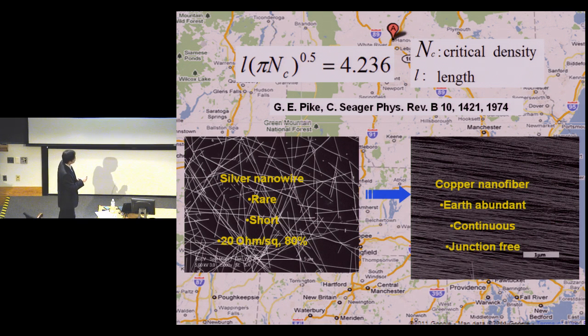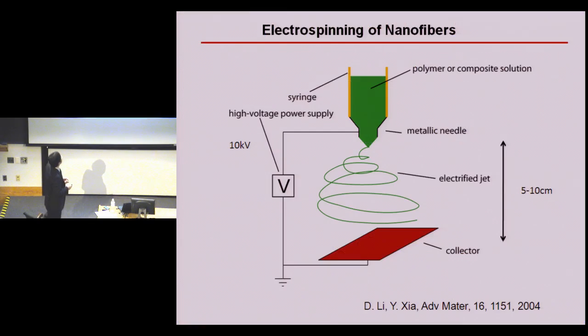So I'm going to show you another example of using this kind of long fibers with fused junctions, which can function as an effective transparent conductor for solar cell application. The way to fabricate this kind of continuous fiber is very simple. It's just like the way you make spaghetti. Basically, we have copper acetate mixed with polymer in a solution, and then we push this solution out through a needle. Meanwhile, we apply a large electrical field between the needle and the collector. As the wire shoots out from the needle, it will spin around, travel a long distance, and be fully dried before it hits the collector. So let me show you a movie to show the process of electrospinning.